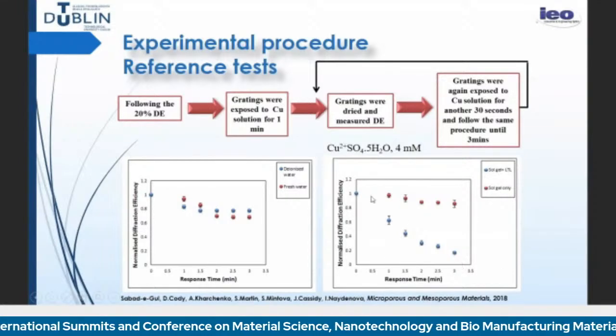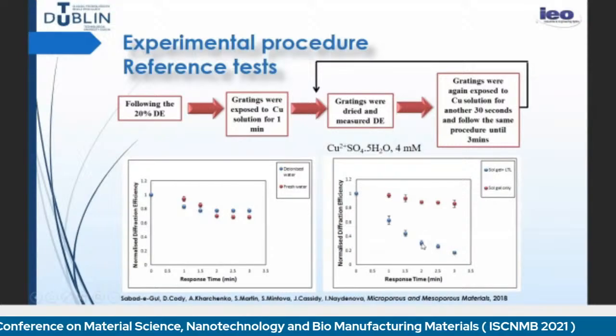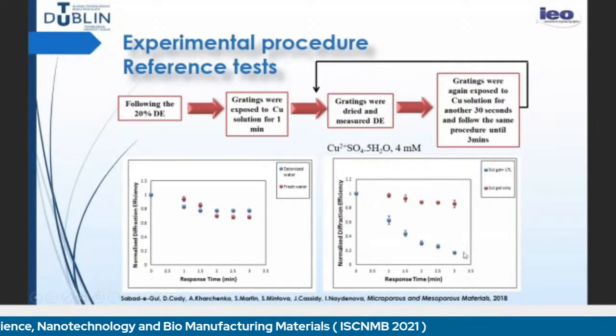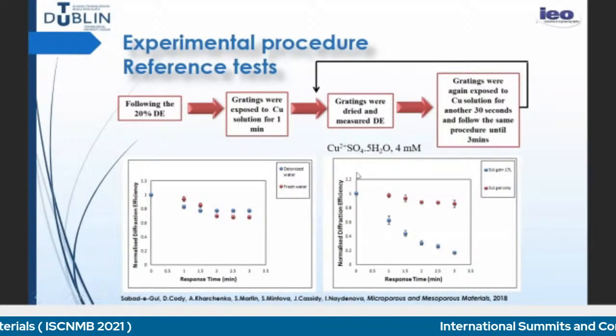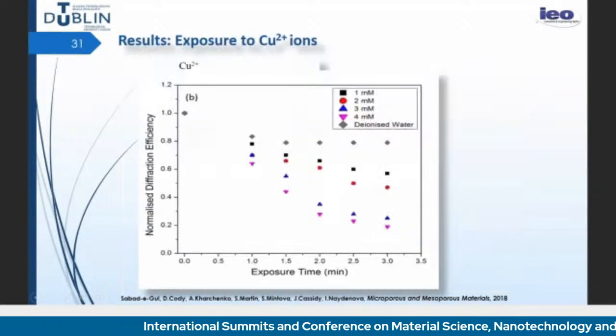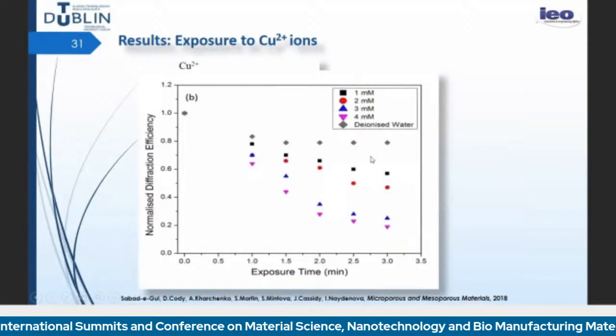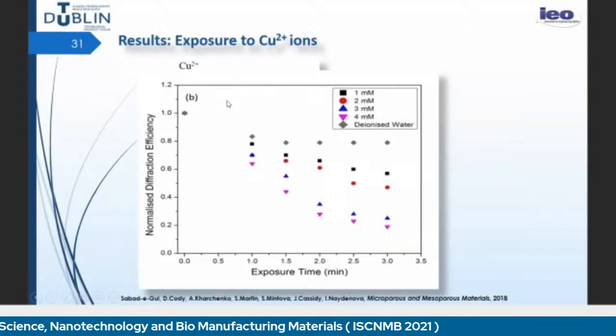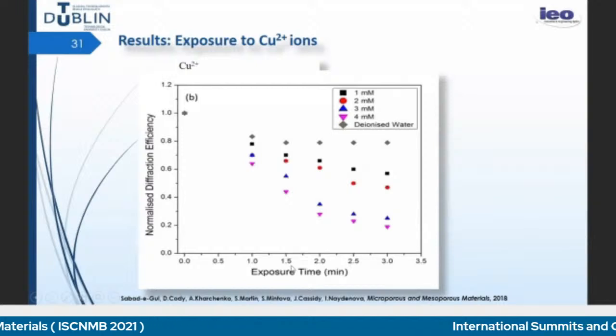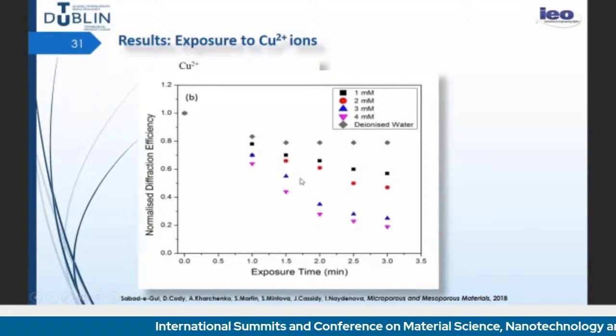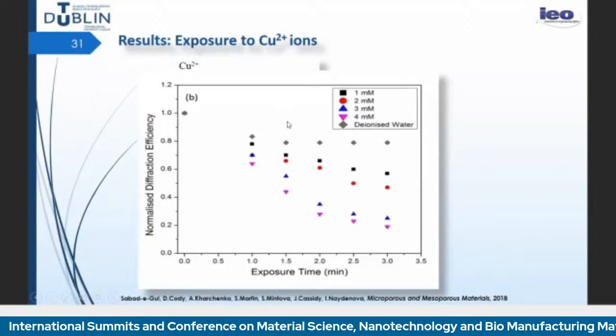And we see that the change is much larger in this case for the sol-gel with LTL. So the element that is detecting the copper is really the sol-gel, not so much the LTL nanoparticles. So these are results for exposure to copper ions with different concentrations. This is the reference in the deionized water, and we see nicely how it depends on the concentration. And actually, already here in 1.5 minutes of exposure, we distinguish well between the different concentrations.